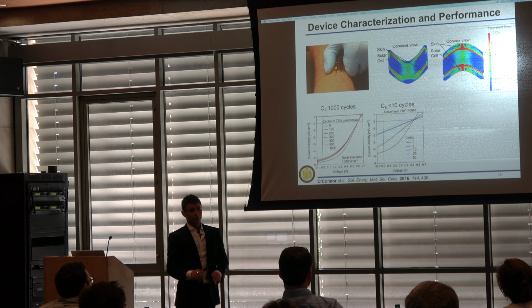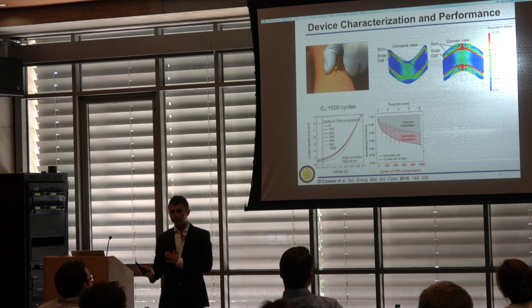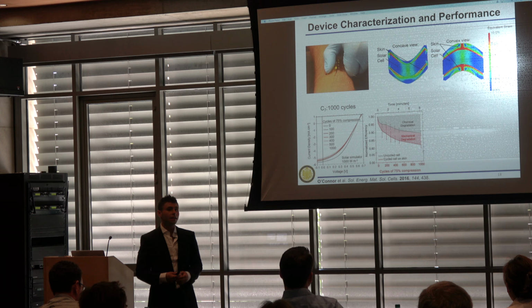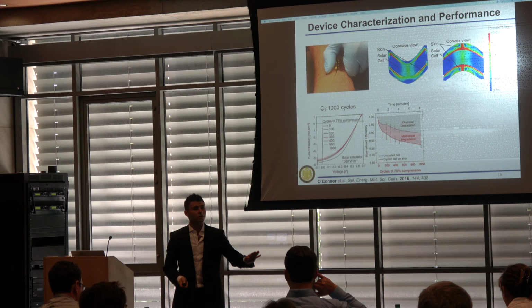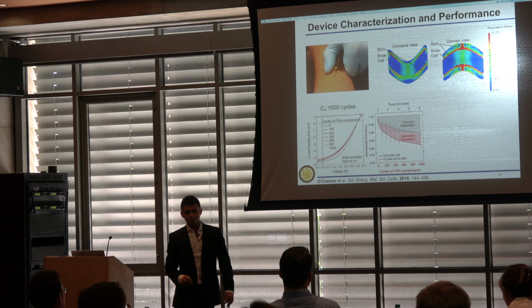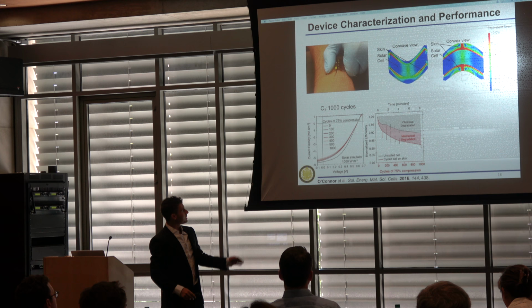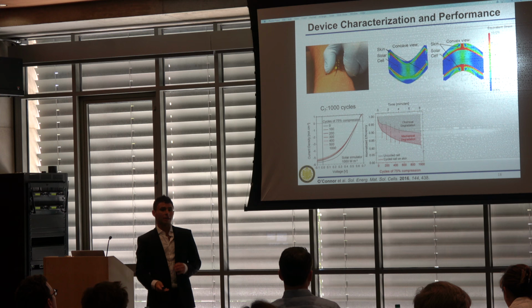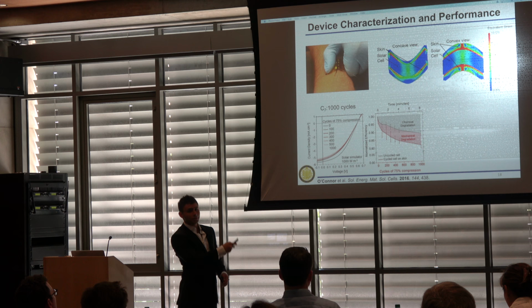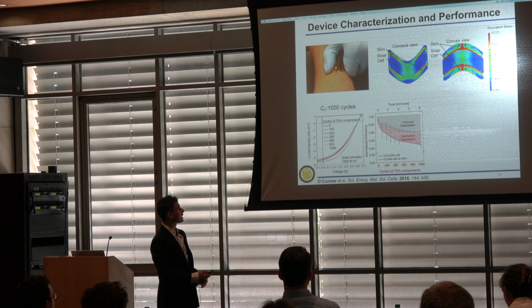We then wanted to decouple mechanical degradation from chemical degradation. Since these devices were out in air and unencapsulated, there would be two different types of degradation mechanisms. In order to do this, we had some uncycled cells that we left on the side, and we watched the degradation occur. And what we noticed is after about 200 cycles, these two degradation curves become more or less parallel. So it shows that within the first 200 cycles, mechanical degradation attenuates, and from this point forward, it was just chemical degradation. So even after 200 cycles, this evidence would support that the degradation had stopped, and you'd actually be able to continue cycling it without any negative effects to the performance.